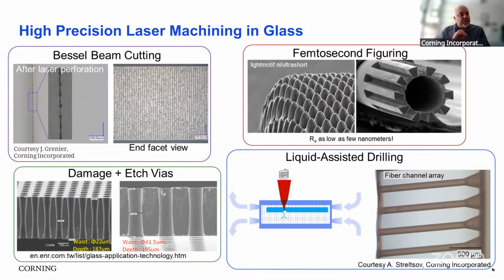In order to very precisely and with low roughness figure materials, you cannot beat femtosecond figuring. This can apply very smooth, nanometer level roughness if you've got time to do it. And then you can even use more sophisticated processes such as liquid immersion if you want to mitigate thermal effects and create complex, long, high aspect ratio channels.